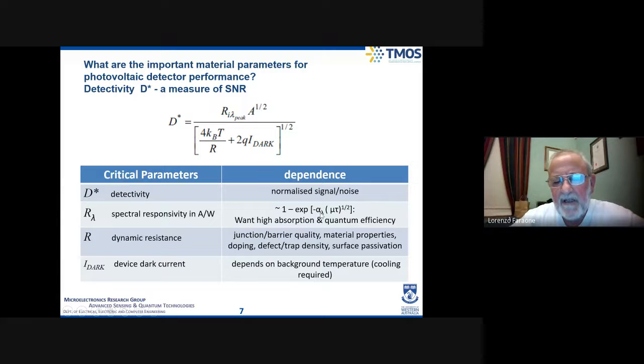What this means is that if I have a good absorption coefficient, it means that I'm absorbing photons and generating electron-hole pairs. What the high mobility and long lifetime gives you is it means that I can collect those electron-hole pairs, which gives me my photocurrent in my responsivity.